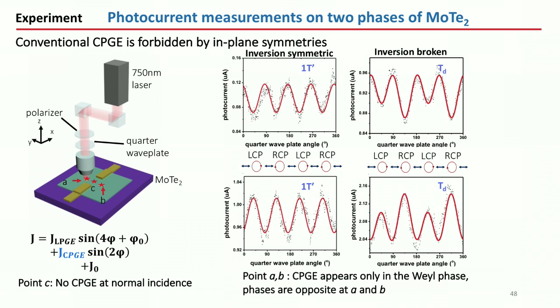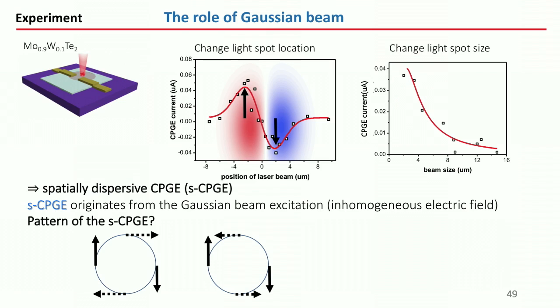But the moment we take it to the Weyl semimetal phase, left and right circularly polarized light have different responses, which means it now shows the circular photogalvanic effect. But interestingly, what we found was, if we shine light here versus here, so these are the two electrodes, and we connect them but apply no bias, then when we shine on this point and its symmetry counterpart on the other side, the phase of the signal basically reverses. This is low, this is high, and opposite. So something different is happening.